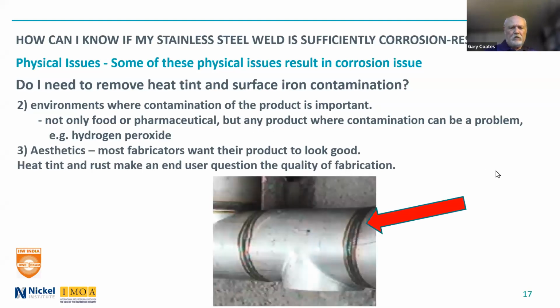And if you have heavy heat tint such as this, okay, that's on the outside of the pipe. Maybe that won't have any effect on the outside in the particular environment that it's exposed in. But if I see that, it raises a red flag for me: how good is the inside weld surface? How much heat tint is there? Does this fabricator really know what they're doing if they allow this to occur? If that heat tint had been removed, you probably wouldn't have thought about it, but by just shipping it, as I say, it may have no effect on the outside, but you certainly have concern for it on the inside.